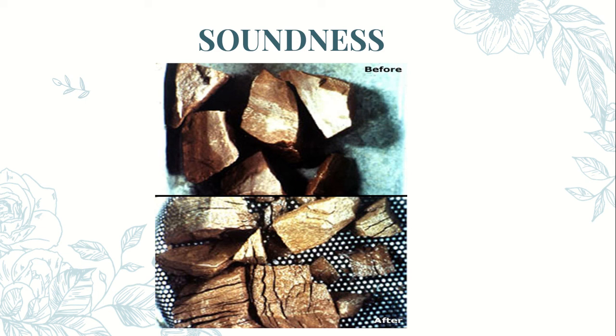So how is the soundness test performed? The soundness test is performed by submerging the aggregate sample in sodium sulfate or magnesium sulfate solution. This process causes salt crystals to form in the aggregate's water permeable pores. The formation of these crystals creates internal forces that apply pressure on aggregate pores and tend to break the aggregate. What you can see in the first figure.